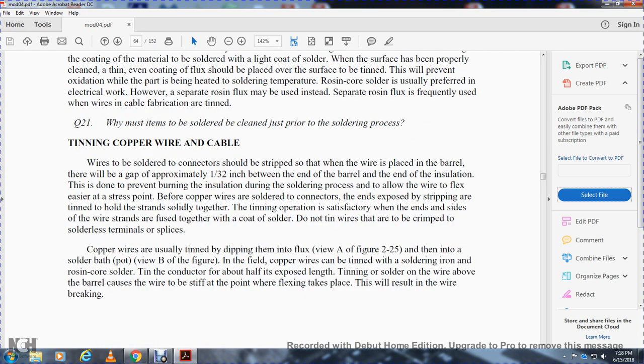Wire should be stripped so that when it is soldered into a connector, the wire is placed in the barrel. The wire gap is approximately 1/32 inch below the end of the barrel, and the end of the insulation is clear. This prevents burning of the insulation during the soldering process and allows the wire to flex easier at the stress point. Before copper wire is soldered to the connector, the exposed stripped area is tinned. The tin holds the strands solidly together. The tinning operation is satisfactory when the ends and insides of the wire strands are fused together and coated with solder. Do not tin wires that are to be crimped to solderless terminals or splices.